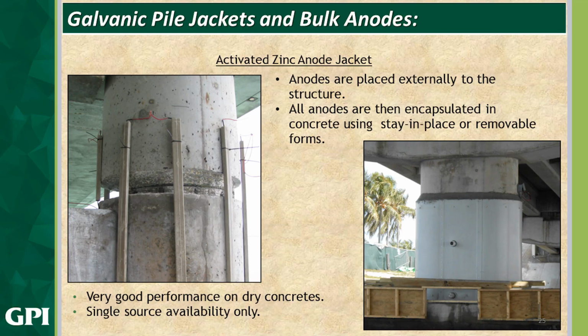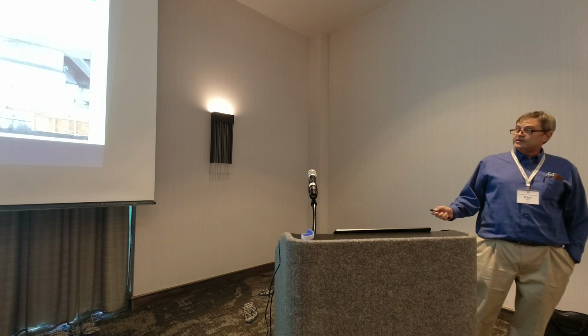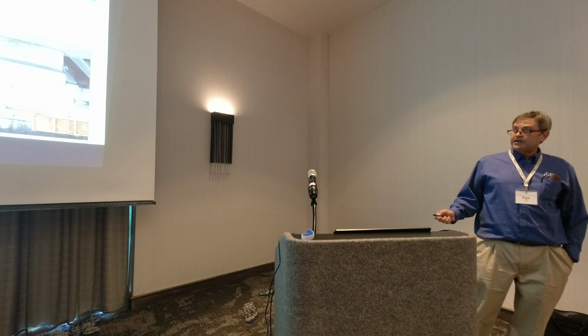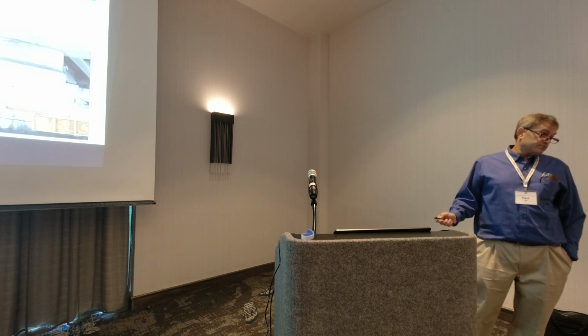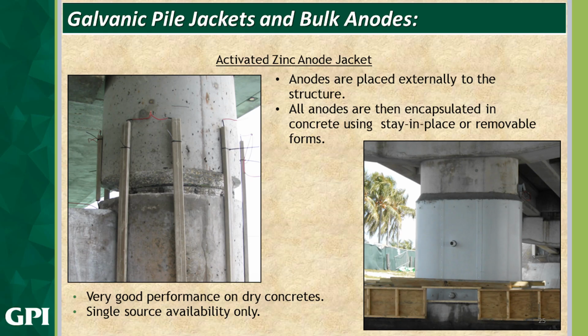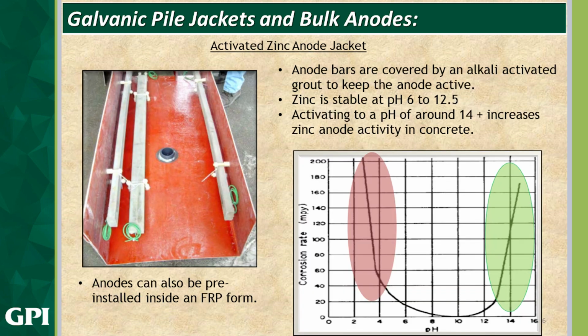So more galvanic pile jackets and bulk anodes. They're activated zinc anode jackets. The anodes are placed externally to the structure. In this instance, you can see them here. The anodes are then encapsulated in the concrete using stay-in-place forms or removable forms. Very good performance on dry concretes, and unfortunately it's only single source availability. Some more pile jackets and bulk anode information. The bulk anodes can also be installed in the jackets just the same as the zinc mesh. Anode bars are covered with an alkali-activated grout to keep the anode active.